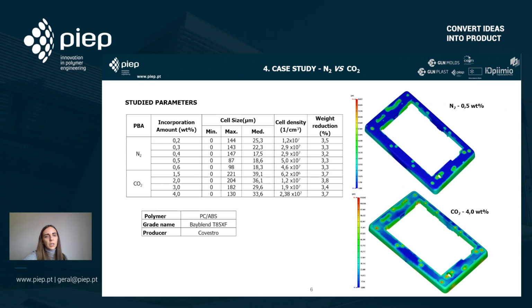So in the first case, the case study with nitrogen versus carbon dioxide, we started the study with different amounts of incorporation, either for CO2 or N2. We wanted to determine which was going to be better for this part. So we evaluated weight reduction, cell density, and cell size. Weight reduction would give us which gas was better to obtain higher amounts of weight reduction, and cell size and cell density would help us predict which was the better cell structure for this part.